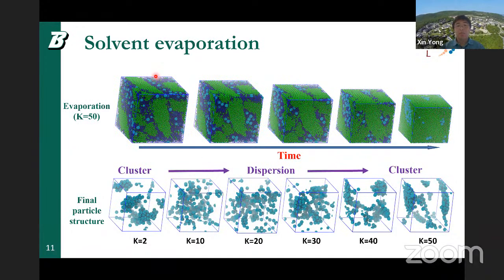As you can see here, now we do plot the solvent, which are these dark blue dots. And as we start to evaporate with this highly rigid system, we see that the particles start to aggregate and start to form clusters. And of course, that's because the space where it resides shrinks as the evaporation of the solvent continues. So by looking at the particle structure alone, we can actually observe a very interesting transition.